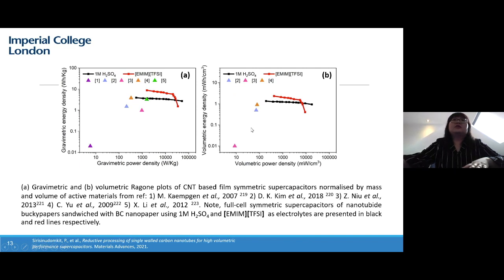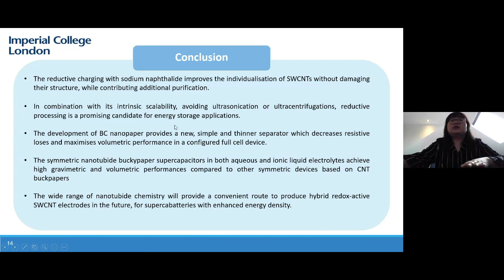So we come to the conclusion that the reductive charging with sodium naphthalide successfully individualizes SWCNT bucky paper and can avoid the sonication or ultracentrifugation that may destroy the structure of the SWCNT bucky paper and reduce its properties. And the BC nanopaper provides a new, simple and thinner separator, which decreases the resistance loss and maximizes the volumetric performance in the whole cell configuration. And this symmetric nanotube bucky paper in both aqueous and ionic liquid actually achieves very high capacitance.